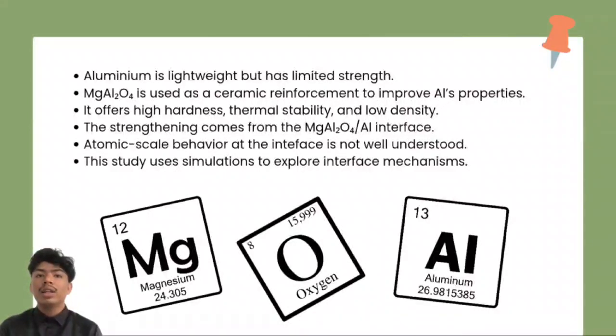When combined, the interface between magnesium aluminate and aluminium becomes of critical importance because it governs how stress is transferred, how dislocations move, and ultimately how strong the composite becomes. However, despite knowing that magnesium aluminate improves the composite's properties, the atomic scale mechanism at the interface remains poorly understood. That's why this study used computational simulations to investigate how atoms behave at the interface, especially during mechanical loading.